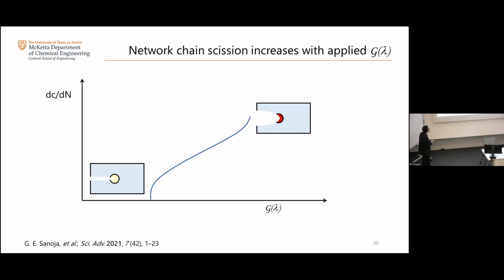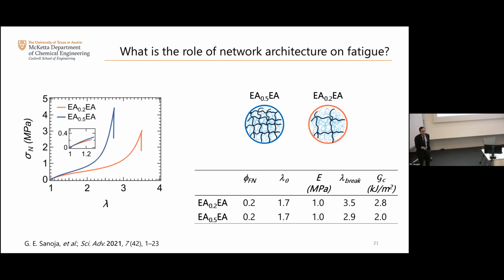crack. Now, this is for one system, but what we think is kind of interesting is to try to understand what happens in terms of molecular design when you start considering multiple architectures. And to do that, I'm considering now 2 double network elastomers. So these are 2 double network elastomers, and they have a different cross-linking density on the filler network. And what's very neat about this system is summarized in this plot. Effectively, your elastic modulus is the same. So the bulk of the material that you cycle around this regime is pretty much the same.